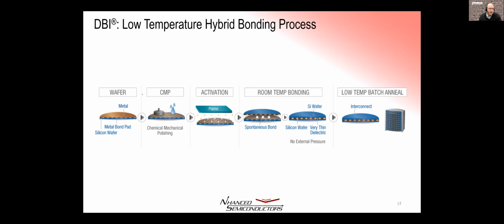You start with a wafer out of the fab. We have a metal bond pad pattern at the top. Usually that is done in copper. It can also be nickel. Under CMP, we polish the surface atomically smooth to typically about 0.3 nanometers RMS. The wafers need to be very planar. They also need to be pretty flat so that they bond well.